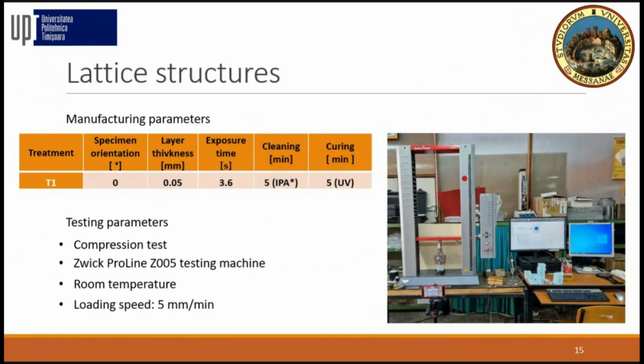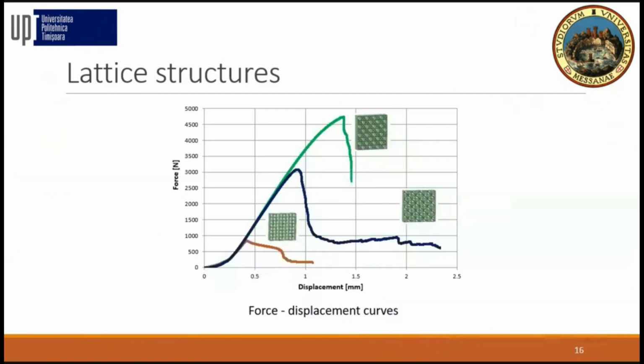So orientation was 0 degree. We use 0.05 layer thickness. Exposure time was decreased because it takes a lot of time if we go for a higher exposure time. And we use the best, let's say, post-curing treatment that we got from the fracture toughness test. We did compression tests. We use our machine from our lab, the ProLine testing machine. We did the test at room temperature with a loading speed of 5 millimeters per minute.